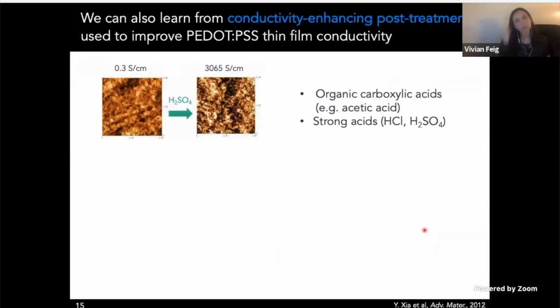And aside from blending with these conductivity enhancing additives, another way that researchers have previously enhanced the conductivity of PEDOT:PSS films is by using post-treatment methods, where they'll start with a spin-coated film of PEDOT:PSS and then rinse them in acidic solutions of things like acetic acid or sulfuric acid. And here the mechanism is really similar, where the preferential interaction of the proton with PSS minus neutralizes the PSS so that PEDOT is now freed up to phase separate into those more conductive morphologies.